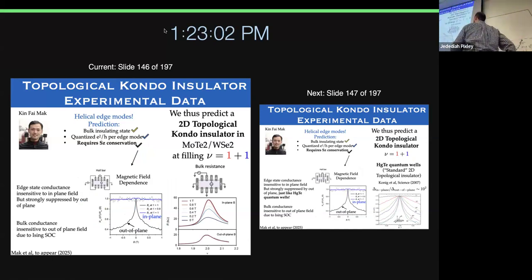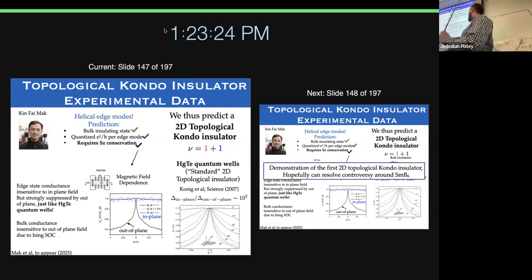So let me show you this one first. So the bulk conductance, if I apply an out-of-plane field, basically along that Ising spin-orbit coupling, it does nothing. If I go in plane, it's a very strong bulk resistance. Now you go to the edge state conductance. So the in plane and out of plane have very different gaps when you break time reversal. In plane is big, out of plane is small. And so this is exactly what's seen in mercury telluride quantum wells, where the out of plane signal drops dramatically. The in plane signal remains constant over this range. It comes down over a larger range. This is a mercury telluride quantum well. It's a 2D topological insulator, quintessential. And look at this. I really think we found a 2D topological Kondo insulator in this material.